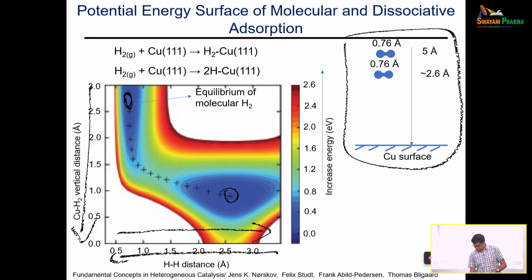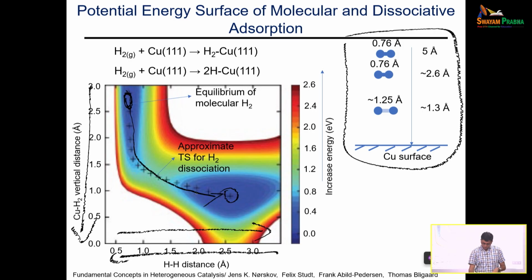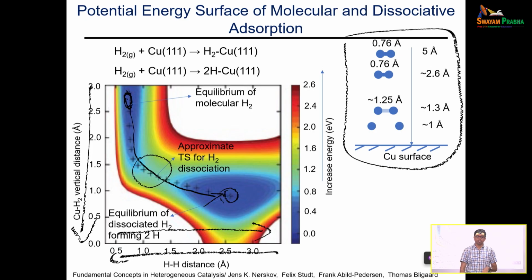If you look at what is happening, there is physisorption here, which is a weak interaction. What you see is, if you trace this path from here, you can see the energy changes. This is becoming more than what it was when it started out here, and it ends up with something which is more negative as well. And if you trace this path, what you are going to see is molecular hydrogen splitting up, and this particular configuration is completely dissociated hydrogen, and what you have at this state is two hydrogen atoms. So effectively you can call this dissociative adsorption of hydrogen.